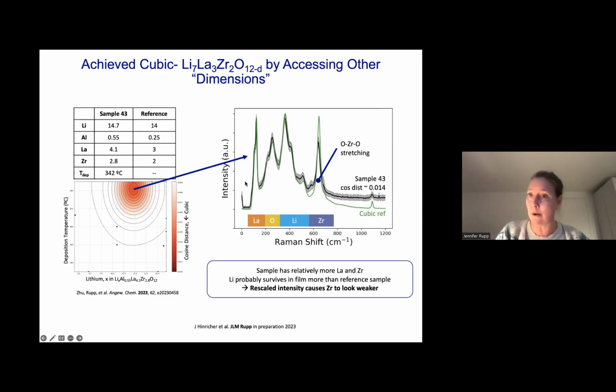And this is really terra incognita. These boundaries are actually not known, and we try to map them. For instance, you can see this is where the lithium oxygen tetragonal and octahedral bond vibrations are in the lithium garnet structure. And we can map now by how much those vary. When you dope, for instance, with tantalum in the system, which is often done to get the highly conductive cubic phase, you affect the zirconium oxygen stretching bonds quite well, and in turn also the lithium vacancies. So these bonds start to vary much more statistically when we do these tests, whereas the lanthanum oxygen bonds always remain at the same wave number, very unaffected.